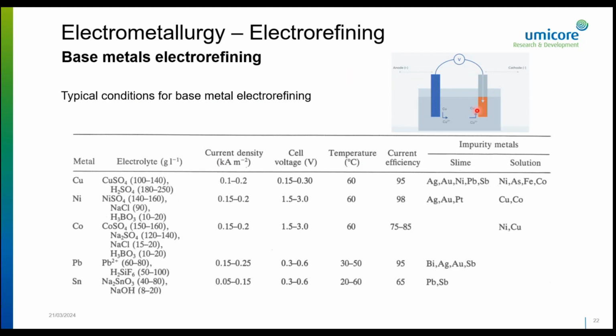In electrorefining, you have the combination of electroleaching and electrodeposition. Where we had oxygen formation as the anode reaction in electrowinning, here we actually have the anodic reaction, the oxidation of the metal and the dissolution of the metal in the electrolyte. And the cathode reaction is the same. We deposit the clean metal. This is actually a way to purify a metal, because you can have an impure anode with a lot of impurities in it, and you can deposit a very pure metal. For instance, most copper is processed in this way. Another big advantage of this process is that, as you can see here, the cell voltage is very low.